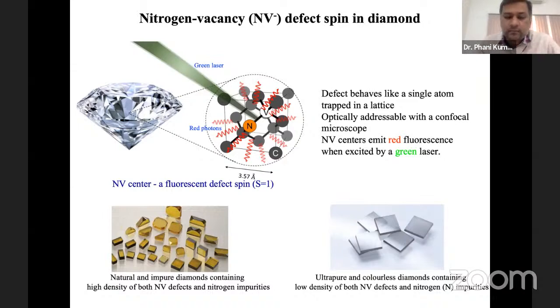So these NV centers can be optically addressable even at the single defect level with a confocal microscope. When we excite them with a green laser, they emit red photons. As I already mentioned, it has a spin. So a spin of S equal to 1, which means that there are 3 magnetic sublevels. One very crucial property of this NV center is that the fluorescence of these NV centers depends on the spin state in which the NV center is present. So this can be used for measuring magnetic fields using electron spin resonance experiments.